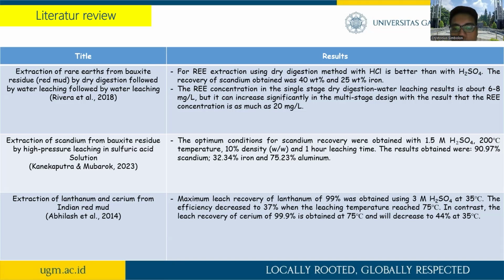2014. Maximum leach recovery of lanthanum of 99% was obtained using 3 molar sulfuric acid at 35 Celsius degree. The efficiency decreased to 37% when the leaching temperature reached 75 Celsius degree. In contrast, the leach recovery of cerium of 99.9% is obtained at 75 Celsius degree and decreases to 44% at 35 Celsius degree.